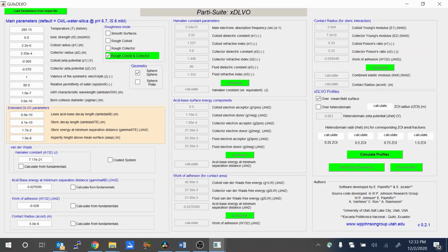A number of studies have shown that the nature of roughness is that smaller asperities are superimposed on larger asperities, and that the reduction in the interactions, whether cast as forces or energies, decreases with the addition of asperities, but non-monotonically, so that asperities increasing in size from a few to a couple tens of nanometers have their largest effect, that is, produce the greatest decrease in the interactions.